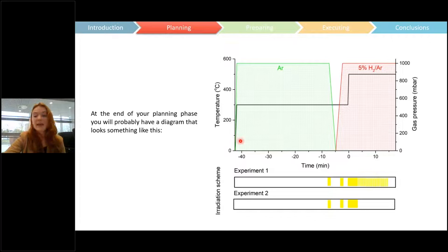In my case, because I love to include that drying step to prevent any silica buildup that we mentioned, I like to have a good long drying phase at 300 degrees here, because my sample can take it. Yours might be down at 100 degrees. It might be somewhere in between, I don't know. But I like to have a good long flushing and drying phase at the beginning, where I make sure I've removed any water so that that's not influencing my reaction. And then I like to ramp very rapidly to the temperature that I'm going to run my experiment at.